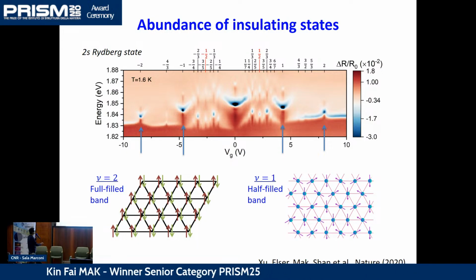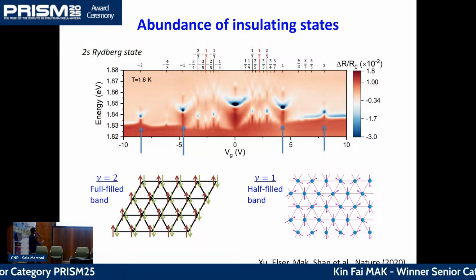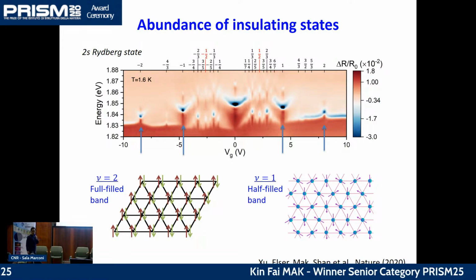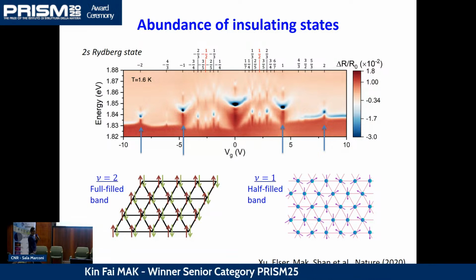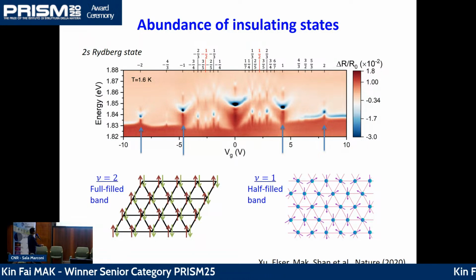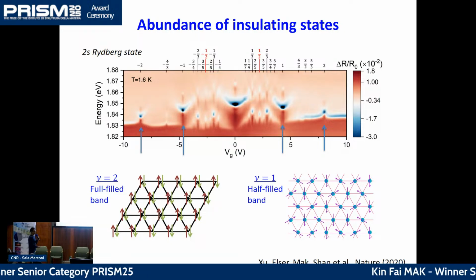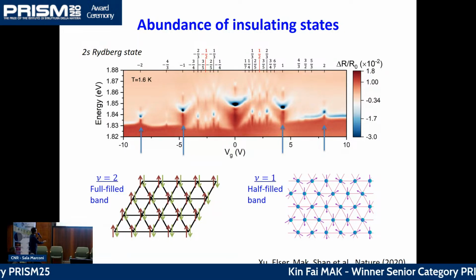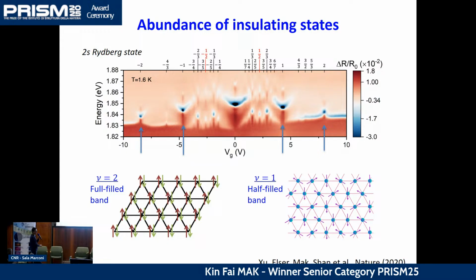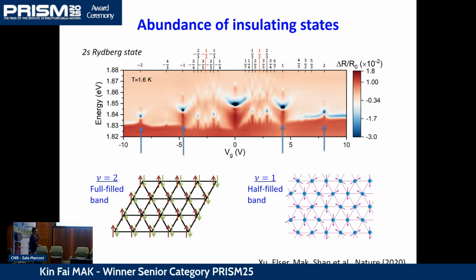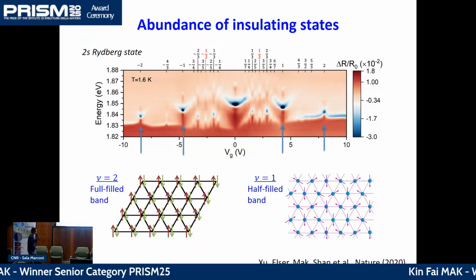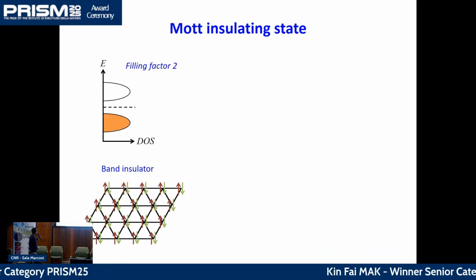For instance, we have this state here with filling factor 1 and filling factor -1 here. The notation is that you fill 1 electron per triangular lattice site in the system. So that corresponds to a half-filled band. And the filling factor 2 and -2 corresponds to filling 2 electrons per site. So that's why you have 2 arrows here. And that corresponds to a fully filled band. Let me explain a little bit what these insulating states are.